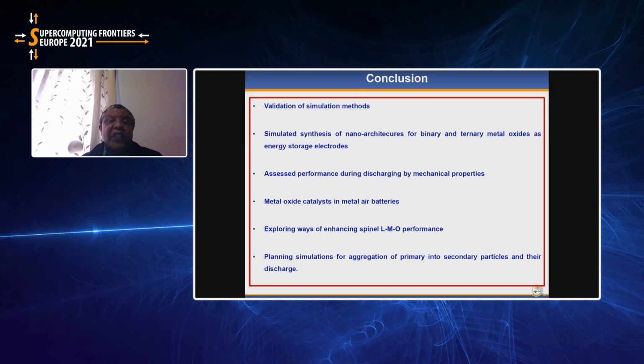So we have looked at the way in which these simulations can well be validated by experimental results. We have seen how we can generate complex microstructures together with the nanostructures using these special methods. We can also look at mechanical properties, which show how the systems behave during charging and discharging. The big challenge is to see how we can enhance the spinel performance by going through that transition, which I call 1.75, in order to get more performance out of the spinel structures.